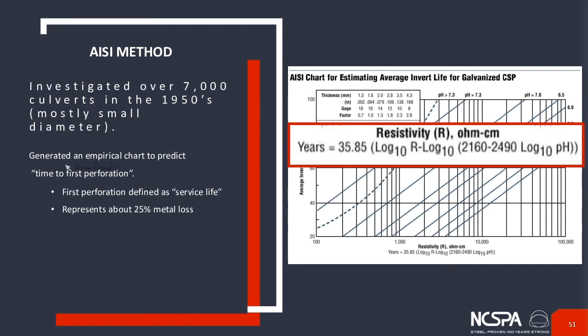Now, AISI took a slightly different approach to the data, and what this slide illustrates is you have all of these lines, and then the curves are generated through this equation here. So this equation will help you plug in, and then you have gauge factors that, obviously, if you have a thicker gauge, you're going to see longer service life. So for this particular chart, 18 gauge was the base factor, and then as thickness goes up, the multiplier goes up. So 16 gauge would be a 1.3 multiplier on the service life predicted from this particular chart.